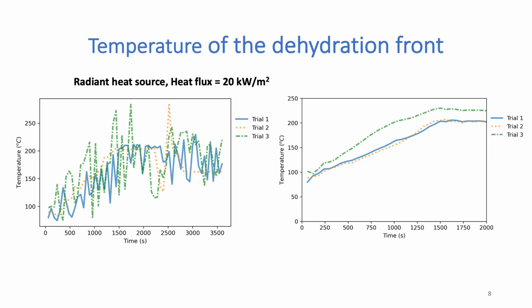Then we looked at temperature of the dehydration front. As this is very difficult to directly experimentally measure, we measured temperature at every millimeter thickness, and we measured the depth of calcination. Based on that, for each minute, we interpolated the measured temperature data for the measured depth of calcination to find the temperature of the dehydration front.